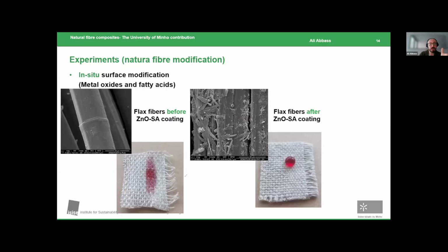And here you would go to the actual effect of this in situ grown microstructure. So here we see superhydrophobic behavior compared to the fibers before the coating. Here I'm using water with a food colorant pigment just to preview the propagation of the droplet within the fibers. So we obtained almost 180 degrees contact angle, which is superhydrophobic, and almost self-washing fibers. This is essential to guarantee the slowdown of the aging in alkaline matrices.